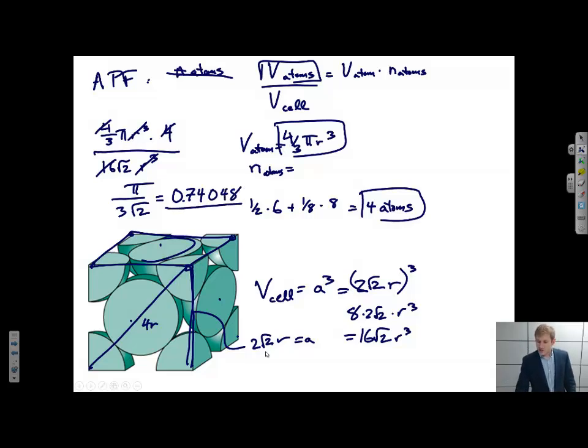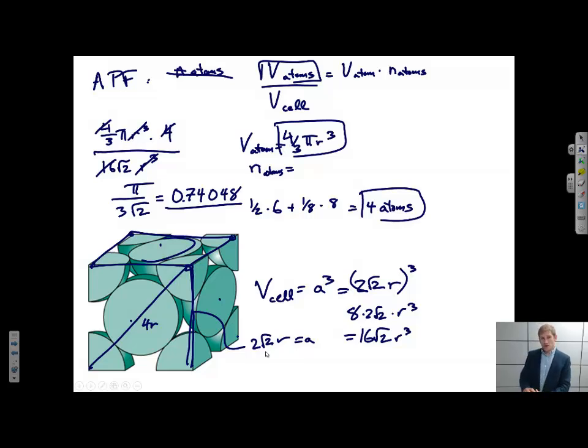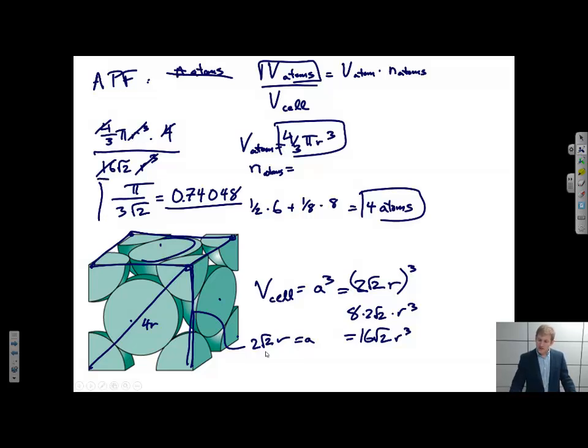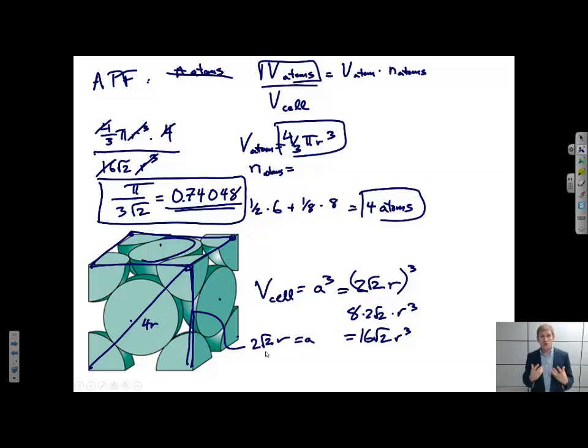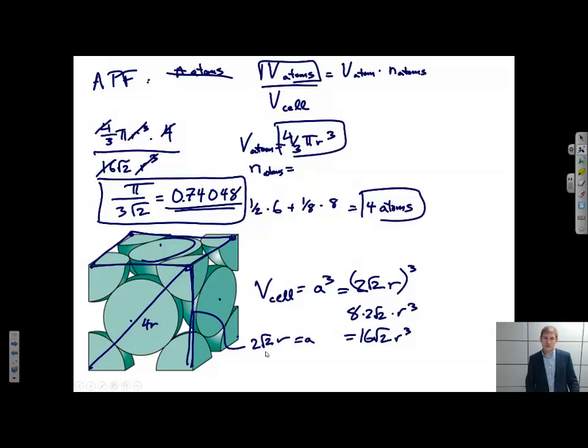You'll notice the radii cancelled out entirely. That's good — when you're doing atomic packing factors, it should be independent of the radii, because whether you use a small sphere or a large sphere, the same fraction of volume is always going to be occupied by the atoms for a given structure. Also, note this number 0.74 — this is what we calculate for FCC, and it's also what you would calculate for HCP, because the two are the two close-packed structures. So they have the same atomic packing factor even though the spheres are arranged in different orientations.